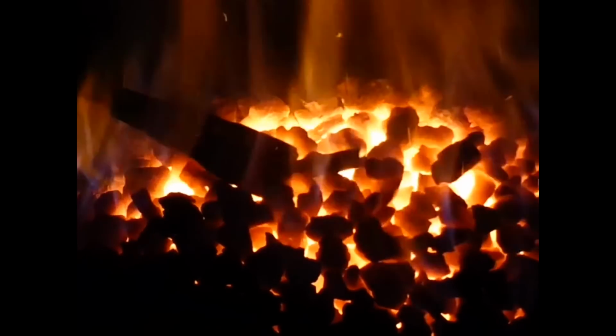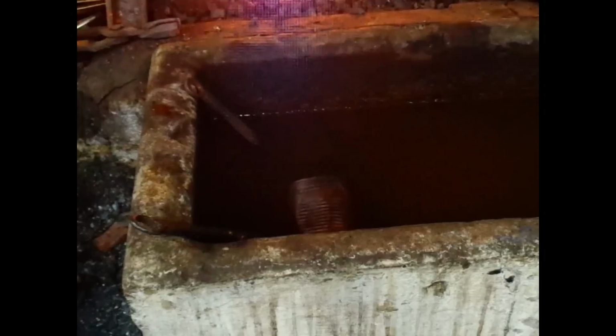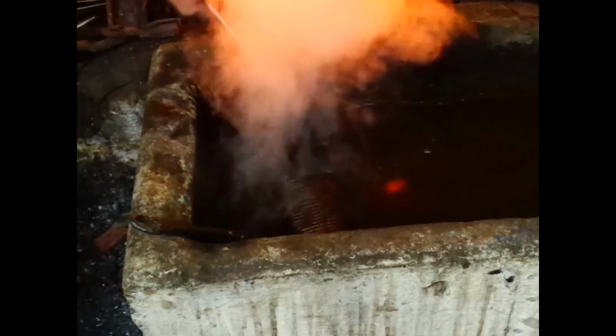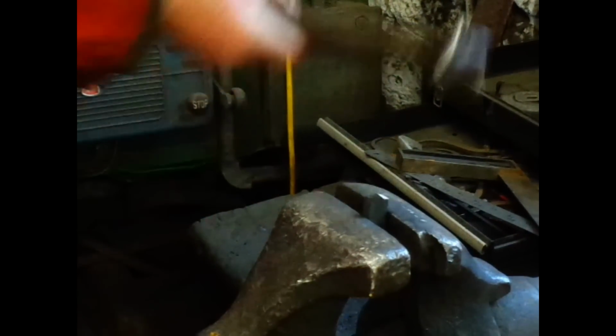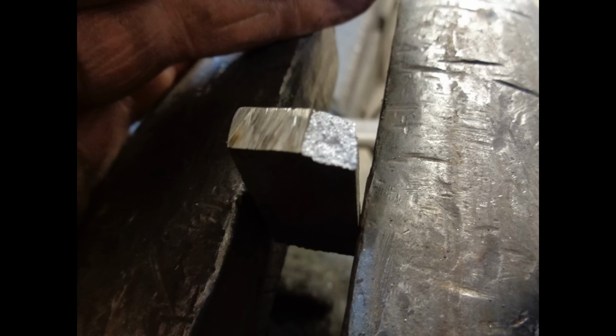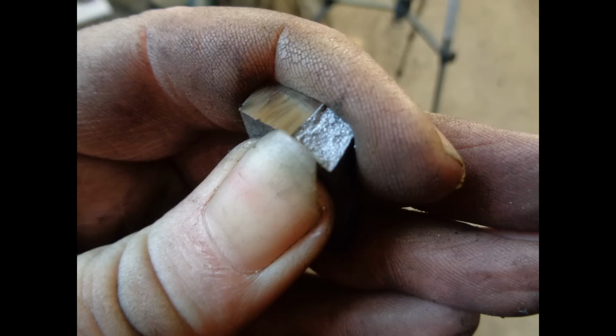To show the grain phases of the steel according to their heat treatment, I made some test pieces as well. The first sample was brought to a bright yellow heat and quenched in cold water. I then nicked it with the grinder and hit it with a hammer. As you can see, the top part just flew off with no effort whatsoever. The grain is very enlarged, which is synonymous with brittleness.